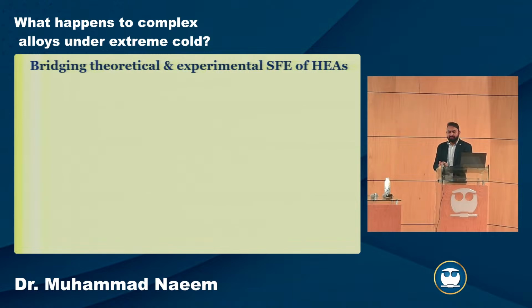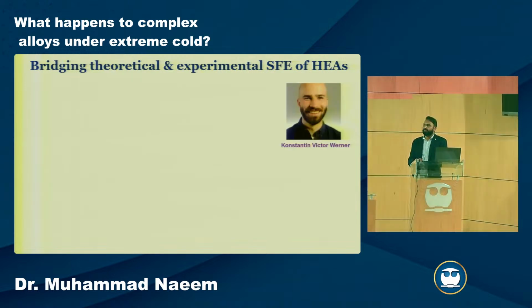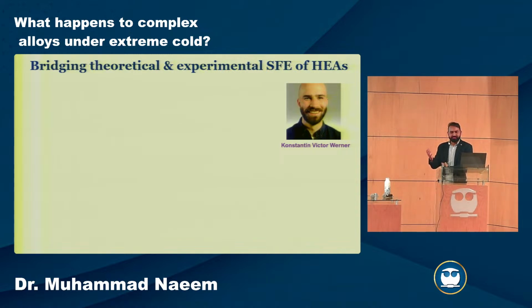But then there was a group of Marcel Sommers at Denmark Technical University, and he had a student who was working on simulations by ab initio, DFT and MD simulation. And the question was, when they do simulation, the stacking fault energy is negative. But when we do experiment, it's always positive. What's the reason? How can we bridge this negative and positive stacking fault energy from simulation and experiment?